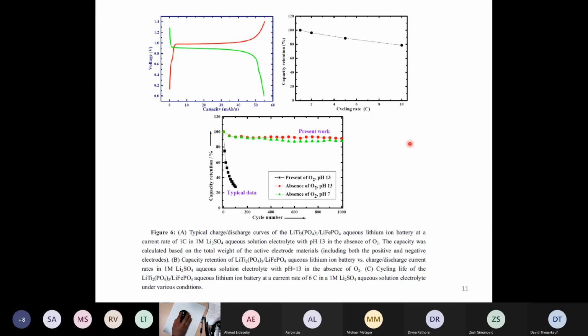So they showed some really quite incredible data. It's about a 1-volt cell, discharge and charge curves. And they showed it could operate up to high C rates, 10 C discharge, giving you about 80% of the capacity of the cell. And then they learned that it was important to get long cycle life to remove oxygen from the electrolyte. So even at basic conditions, pH 13 or pH 7, if you removed oxygen from the electrolyte, things worked really well. But if you had oxygen dissolved in the electrolyte, things did not work well at all.